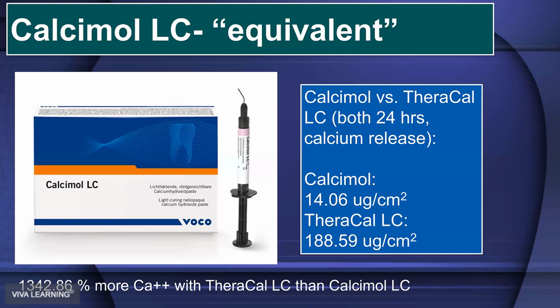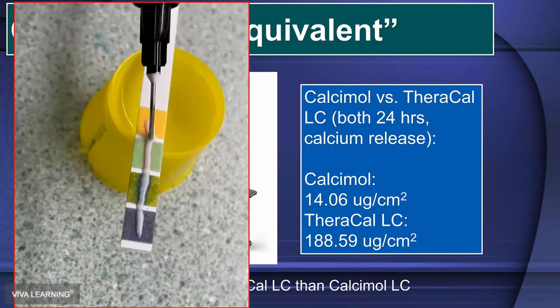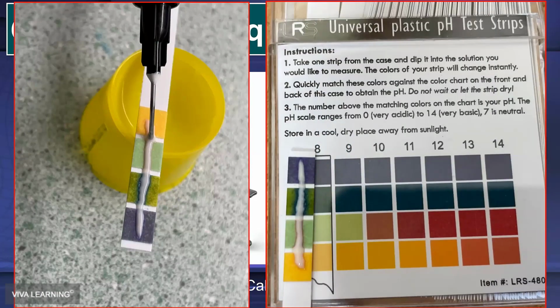TheraCal LC is a tricalcium dicalcium silicate based on a light-cured MTA formulation with a hydrophilic resin base. Calcimol is a urethane dimethacrylate that's hydrophobic with calcium hydroxide in it. In fact, when it was studied, it turns out that you have over 13 times the calcium release with TheraCal LC than you do with Calcimol LC. And look at the pH, barely around 8. That's not good. And when you start off at that, it's going to be neutral in no time.